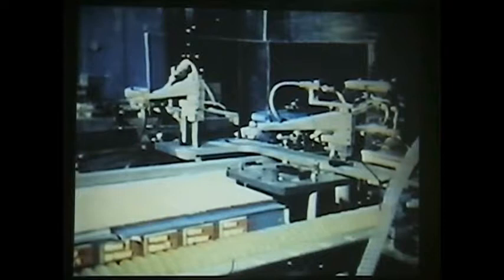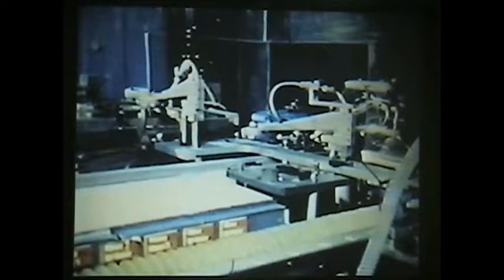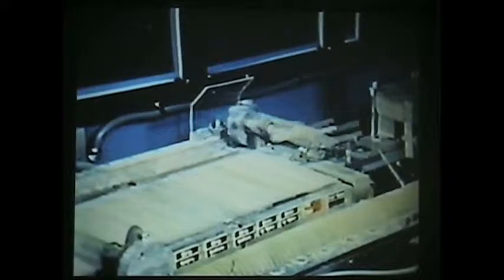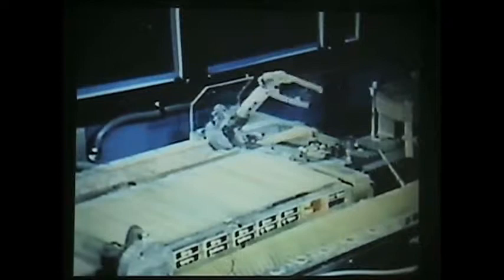And now, after the evaporation of the metal, we immediately put the photoresist on, just like we did in the hot process sectors. And then this wafer at this point, after the exposure of the metal pattern, is ready for etching in the aluminum etch. And since the aluminum etch is very thick, bubbles can adhere to the surface. So we shake it up. And so we shake the wafer and make sure during the etching there's no bubble on the surface.